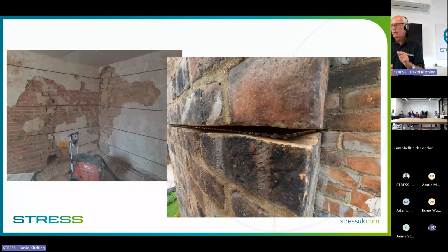The point I want to make on this right-hand photo is, if you're involved in masonry reinforcement, then the quality of the installation is absolutely critical. Because let's say you nipped a bit. We've seen this done many times by others. You nip a bit of the mortar out, you got the bar, you stick it in, and you put some grout in. Well, what's going to bond the bar to the brickwork, which is the important thing, is the mortar that you've left in, the old friable mortar. So you'll have no bond strength. There'll be no transfer of load. You might as well just use duct tape.